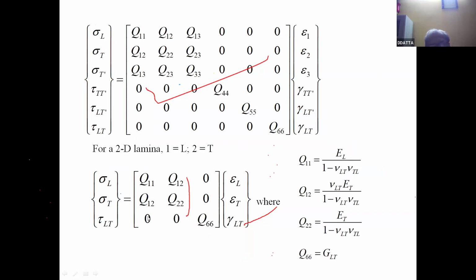We must look into the nature of the stiffness matrix. This is the stiffness matrix because this is the stress vector, this is the strain vector, and this is the stiffness matrix. Now in the stiffness matrix, the first two elements in the third column are 0. Similarly, the first two elements of the third row are also 0. This has a significance. If we apply sigma L, just a normal stress in the longitudinal direction, there will be development of epsilon L. There will also be development of epsilon T, normal strain in the transverse direction because of Poisson's effect. But there will be no gamma LT.